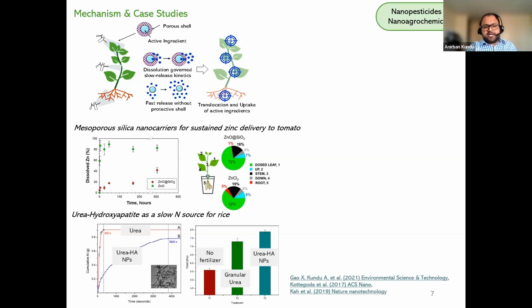There is another really amazing study which is done to test slow release of nitrogen for rice. So similar concept, if you look at the figure on the left, the blue curve is urea hydroxyapatite nanoparticles. So urea is an important nitrogen source. And what these authors did is they interfaced the urea in hydroxyapatite and they prepared this complex. And they found that this complex releases nitrogen over an extended period of time, as opposed to only the urea, which, if present in an aqueous media, led to an immediate burst release.